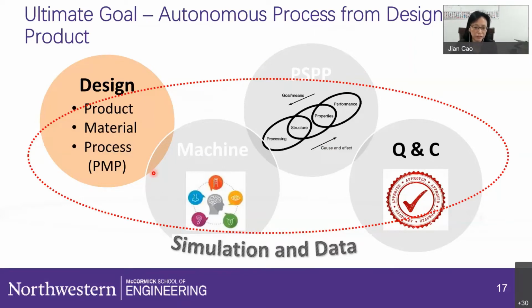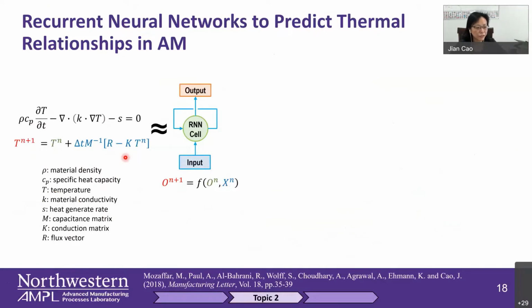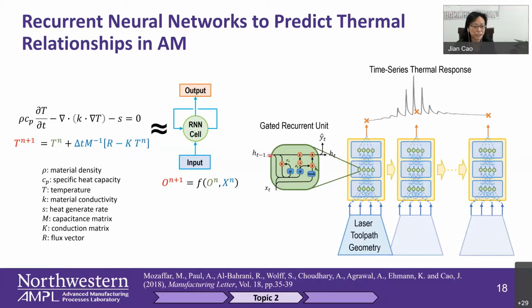So first of all, we developed what we call the Gamma code internally. Basically, it's a thermal code to simulate the DED process. You can see the governing equation right here to look at the thermal behavior of the DED process. And if you look at this, it's very much similar to a neural network, because we have this time dependency, right? So naturally, you will think about using a recurrent neural network to predict the thermal history behavior. So we use gated recurrent units over there and feed in the laser toolpath.